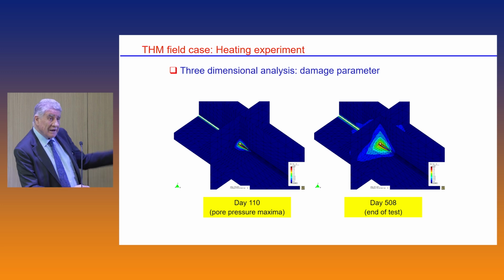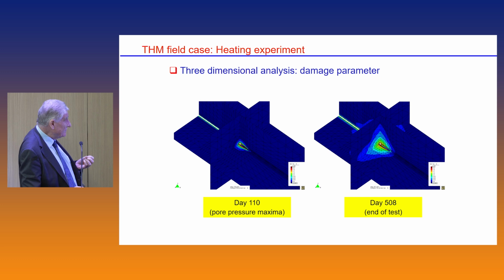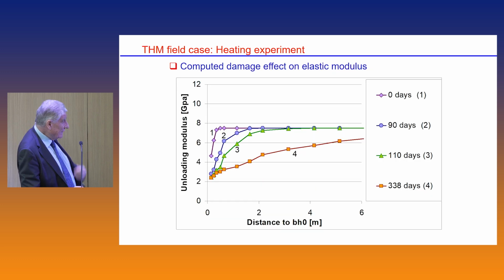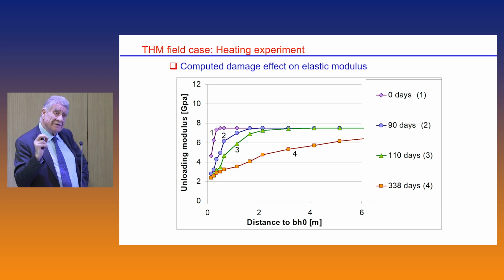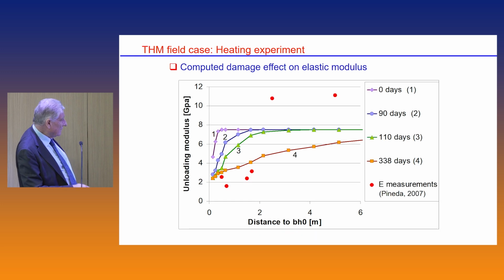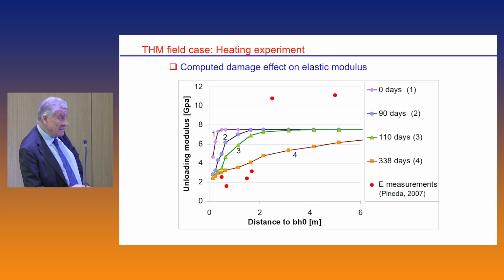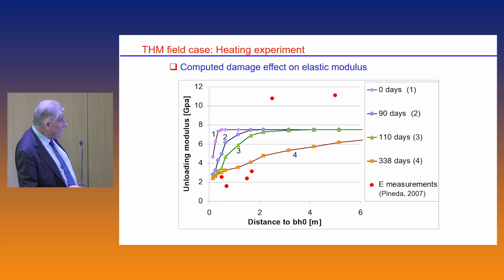I didn't have time to talk about the constitutive model, but there was a damage component, so we could get contours of damage. And we tried to see whether that was realistic. Here we have the distribution of damage at different times. What we did was to get samples at different distances from the heating borehole, and these are the unloading modulus measured in the lab from those samples. These are the predictions. We can see that there seems to be some damage close to the heater, but if anything, we are underestimating that damage.